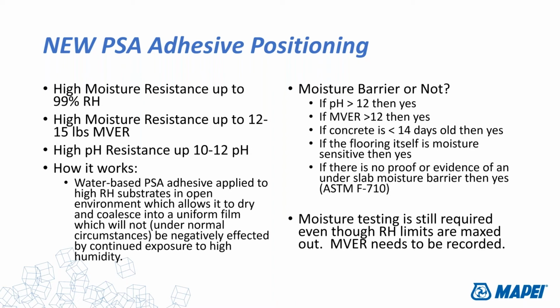Now, how they work is that when you apply a PSA adhesive to a concrete slab, whether it's dry or damp, they're eventually going to evaporate, coalesce, and get down to a pure film of adhesive stickiness that is not going to re-emulsify under normal conditions when you cover it with a floor covering. Even if the slab is 99% RH, these adhesives are designed to withstand that kind of level. But you still need to understand that concrete slab. You need to do your moisture testing to make sure that everything is in line with what's going to be installed on top of it.